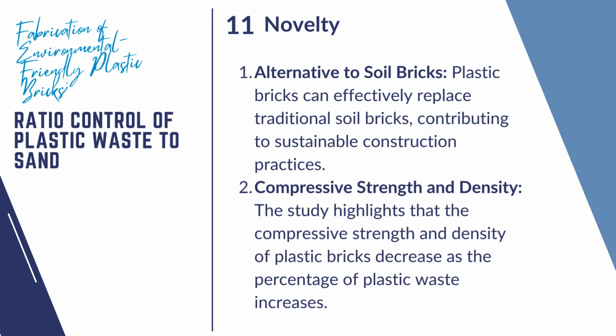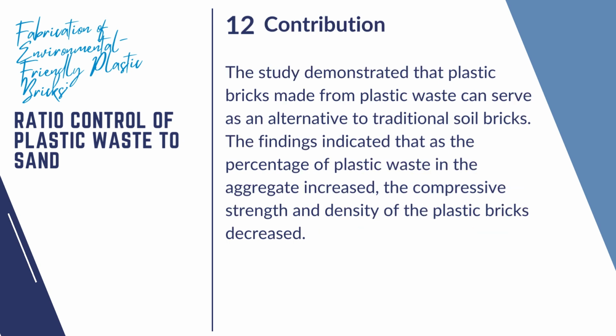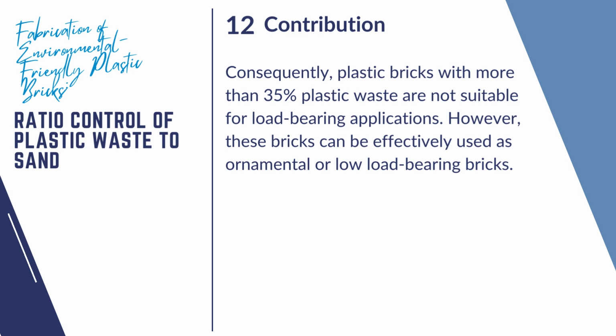The novelty of this study are: 1. Alternative to soil bricks, plastic bricks can effectively replace traditional soil bricks, contributing to sustainable construction practices. 2. Compressive strength and density. The study highlights that the compressive strength and density of plastic bricks decrease as the percentage of plastic waste increases. The study demonstrated that plastic bricks made from plastic waste can serve as an alternative to traditional soil bricks. The findings indicated that as the percentage of plastic waste in the aggregate increased, the compressive strength and density of the plastic bricks decreased. Consequently, plastic bricks with more than 35% plastic waste are not suitable for load-bearing applications. However, these bricks can be effectively used as ornamental or low load-bearing bricks.